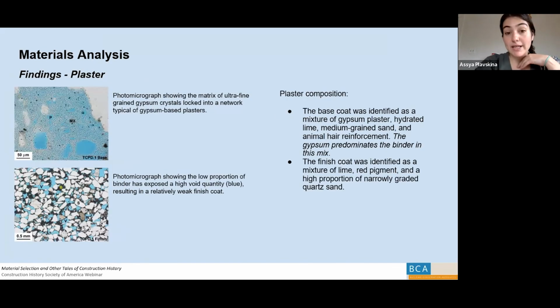So let's talk about some of the findings of our plaster analysis. What you see here are photo micrographs, which show the composition of the base coat at the top left, and the finish coat at the bottom left. What we found about the base coat was that it was a mixture of gypsum plaster, hydrated lime, sand, and animal hair. And the gypsum was actually the predominant binder in this mix, and I'll speak more to that later.